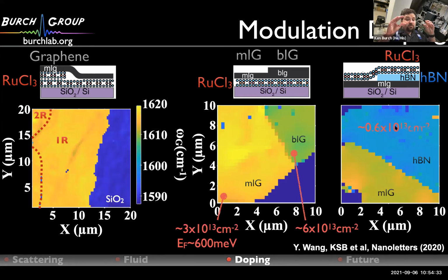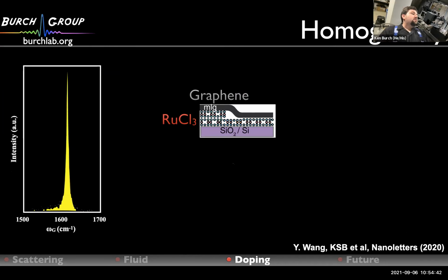But we found that as you reduce the thickness of the BN, you can actually make this doping go up and up and up, as you'd expect for a kind of tunneling process. So what's also nice about this is we can use the Raman to detect the homogeneity. So what we saw was that there are regions that are very heavily doped. And then there are regions where you see both the heavily doped peak and then another peak that looks like it's at the undoped region. And then if you keep going, you would actually see regions that were sort of roughly 50-50.